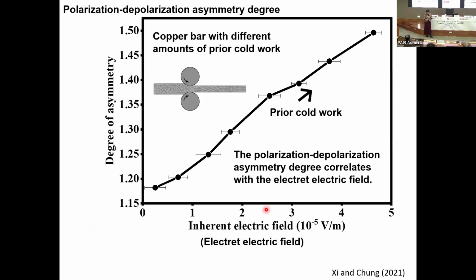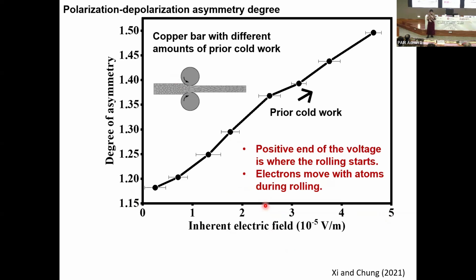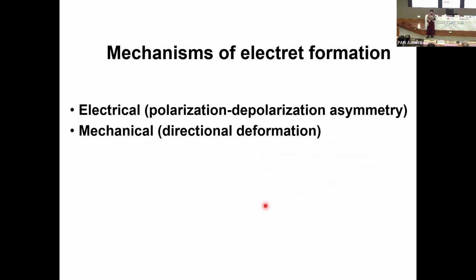Now, if you increase the amount of prior cold work, the inherent electric field increases. And also that degree of asymmetry, what I call polarization, depolarization asymmetry, also increases. So there's correlation between that asymmetry and the presence of the inherent electric field. And both are enhanced by prior cold work. Very importantly, the positive end of the voltage is where the rolling starts. This means the electrons move with the atoms during the rolling. Another clear indication of the interaction between the electrons and the atoms.